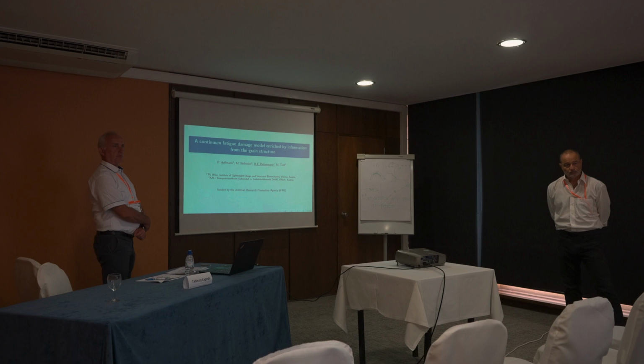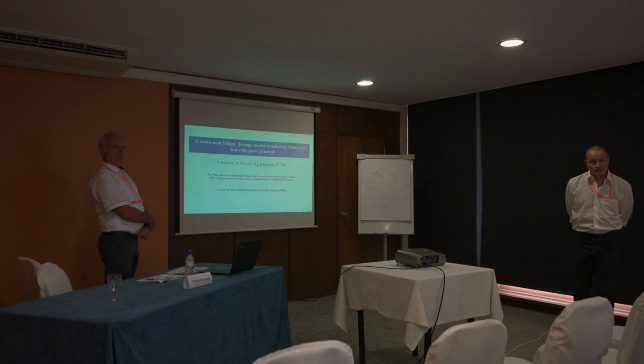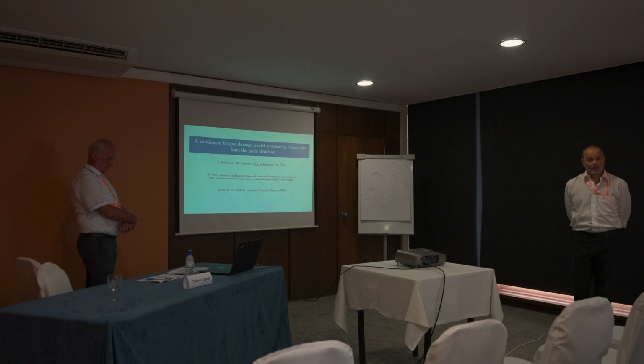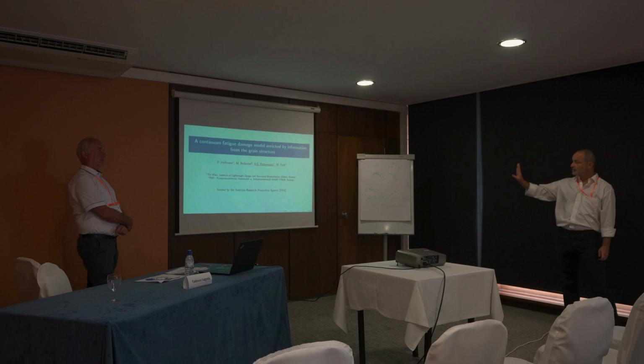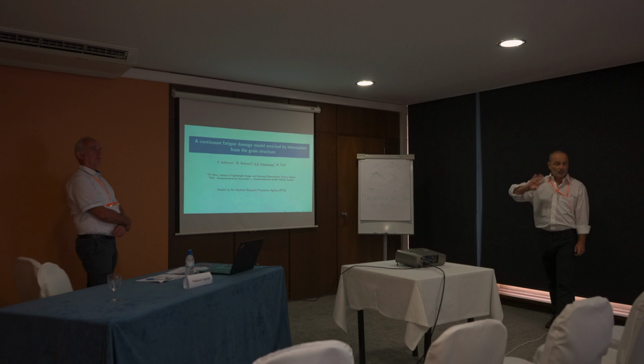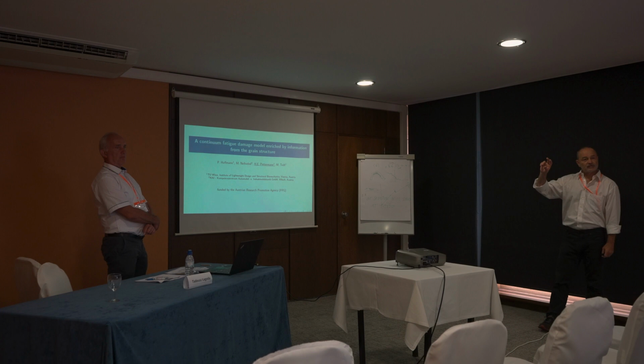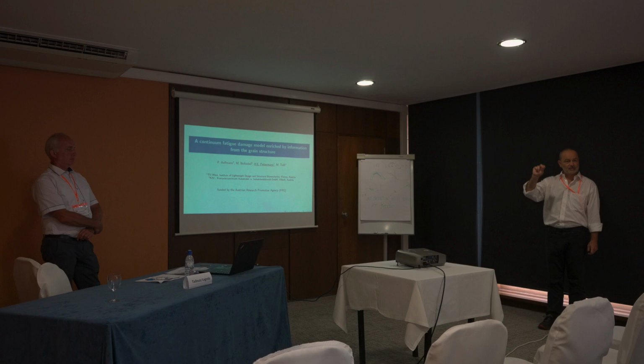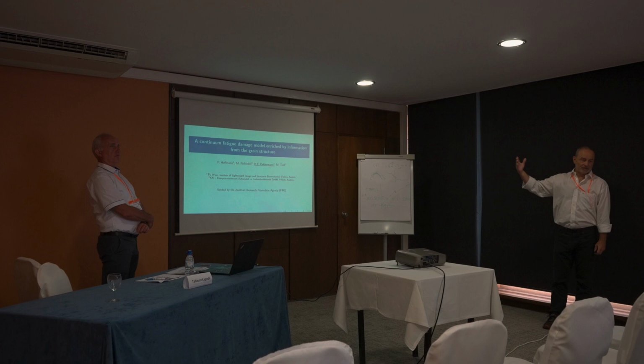Have you inserted a certain parameter H also for the grain boundary? You have a reduced, so to say, lifetime for the triple point? So, yes. And also for the grain boundary, or not? The material itself is homogeneous. We do not have that in the model. The model only knows a homogeneous material, simple J2 plasticity, and we just put a density of triple points and the density of starting points of damage nucleation, which comes from experimental evidence.